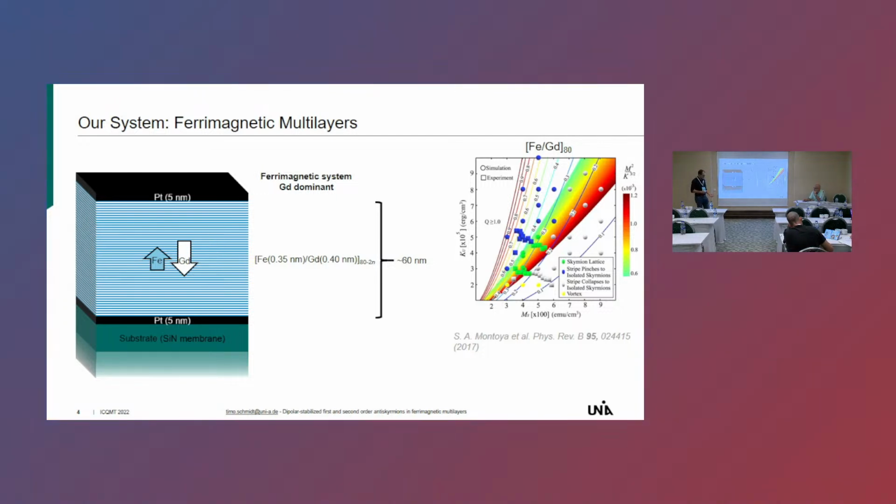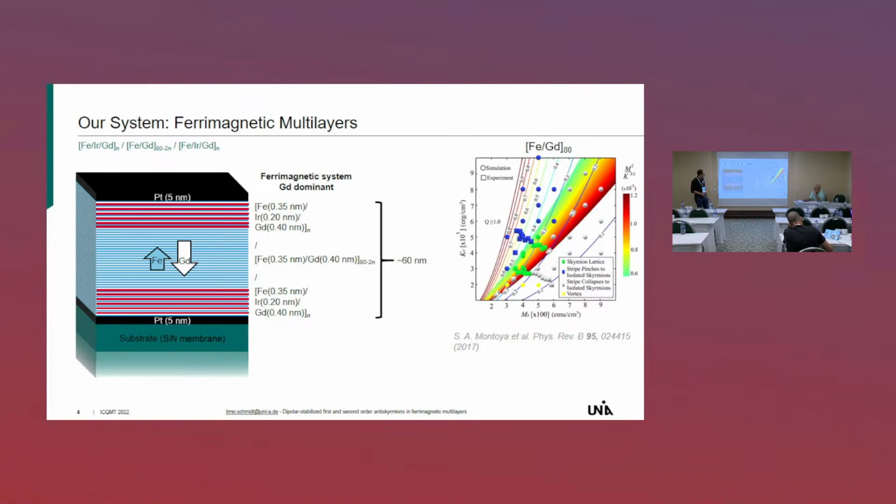And now the approach was, what happens if we stuck iridium layers inside the top and the bottom? Like we made a few samples with different numbers of iridium layers, because iridium has a really strong spin-orbit coupling, and it basically introduces DMI to the system. So we have a Bloch-type characteristic from our iron and gadolinium, and we could have this Néel skyrmion characteristic type, because in the DMI systems, most skyrmions form for a Néel type.